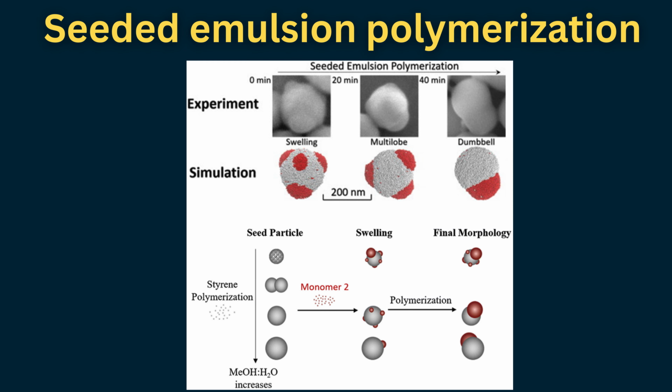For example, amphiphilic JPs can be synthesized through seeded emulsion polymerization, where hydrophobic polystyrene, poly(divinylbenzene), PS/PDVB, domains are combined with hydrophilic silica components. The spatial segregation of these components produces particles with two chemically distinct hemispheres.